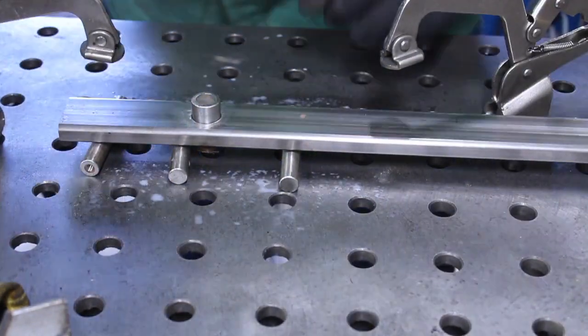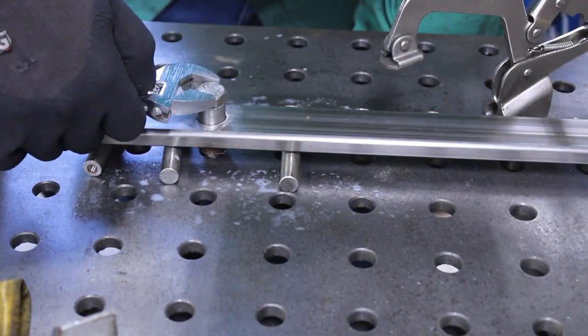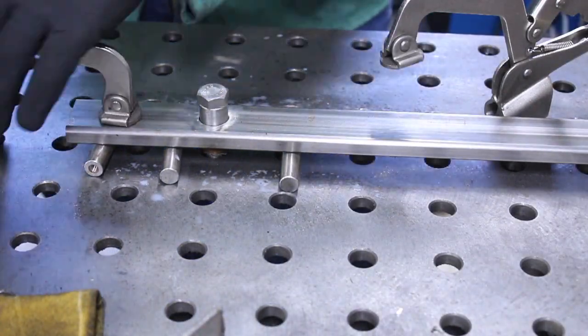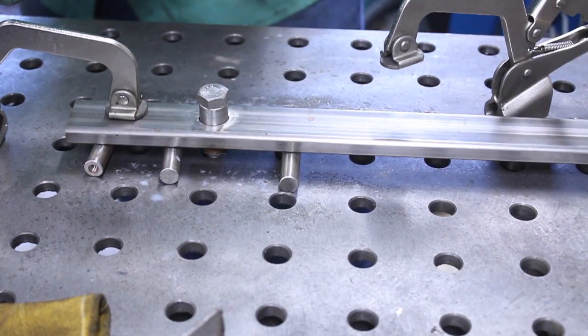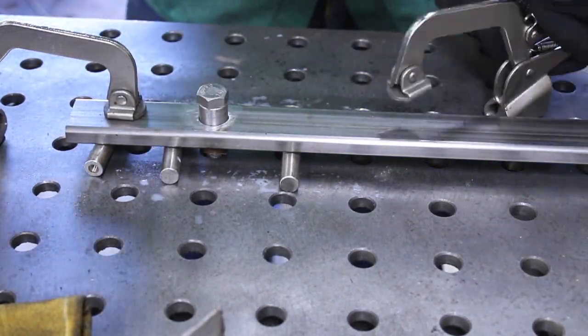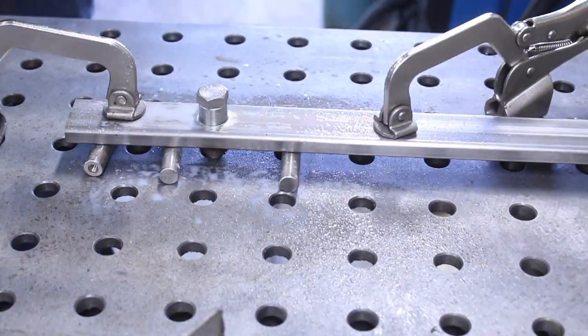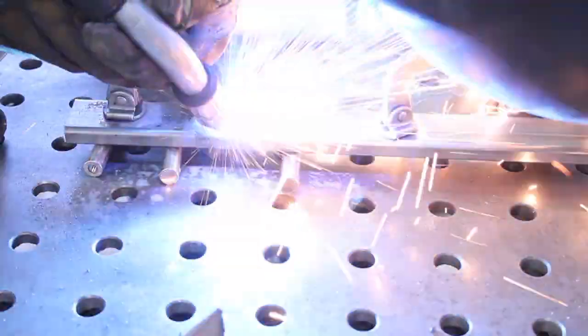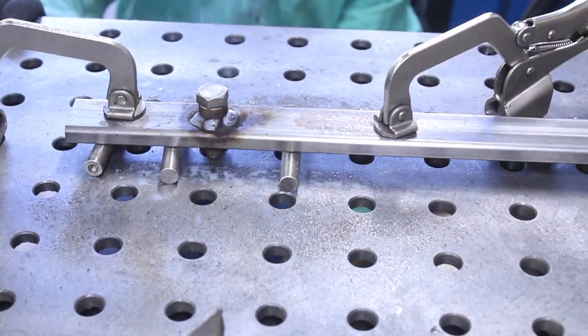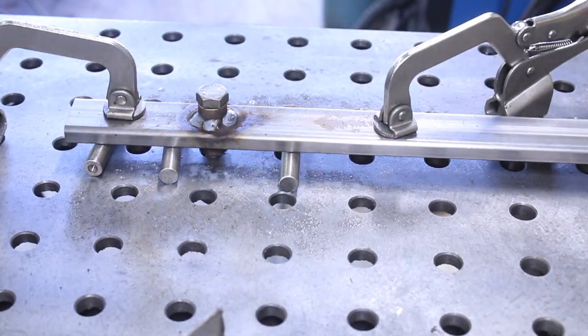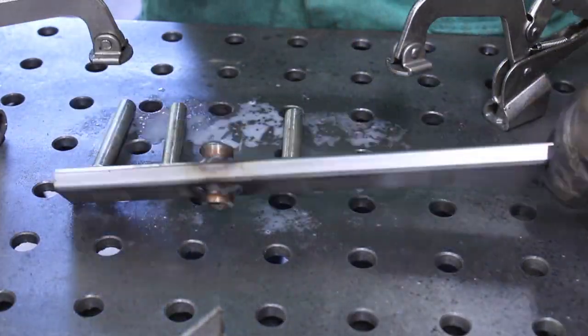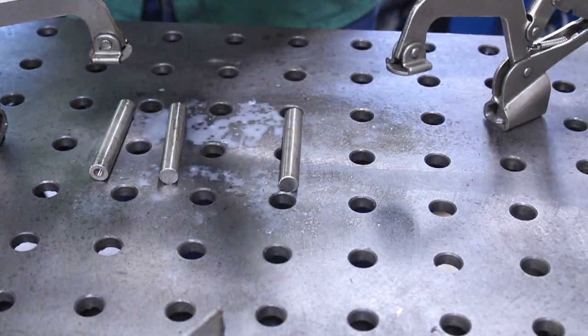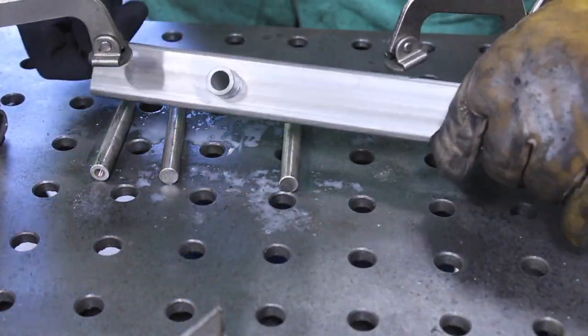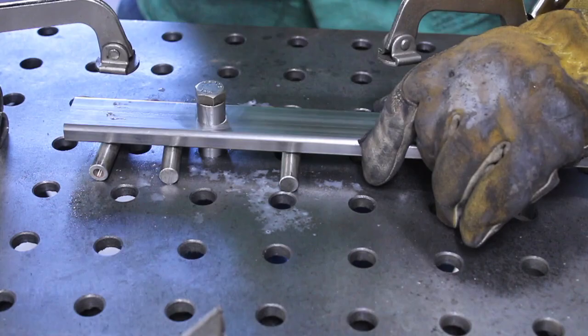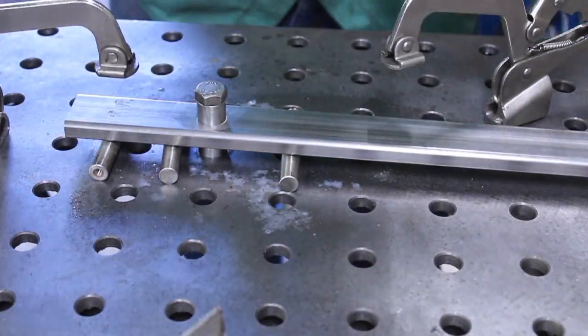You can see during this weld, I'm getting in and getting out, just applying my heat where it needs to be and then moving along. The trick with these welds is your tie-in. There is some backstitching similar to TIG welding, but you can see how the heat affected zone is much smaller because you're punching it so hard. Whereas with TIG welding, you have to sit for a few seconds and establish the puddle on both sides of what you're trying to join, and that's when the heat builds up a little much. And even on chill blocks, weird parts like this, it doesn't pull enough heat out.